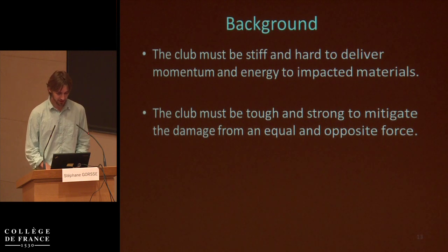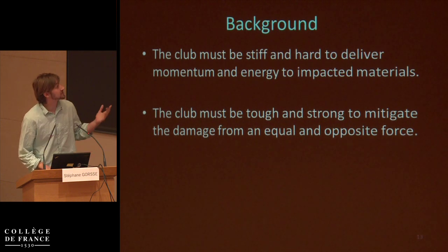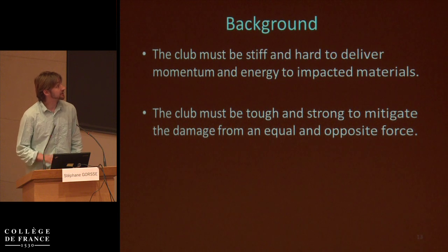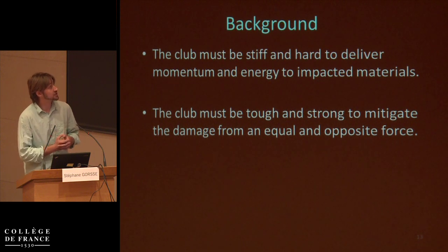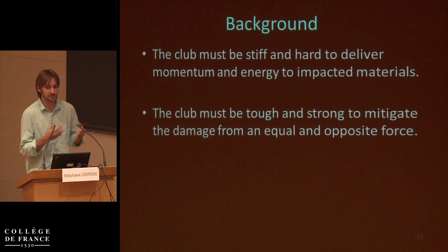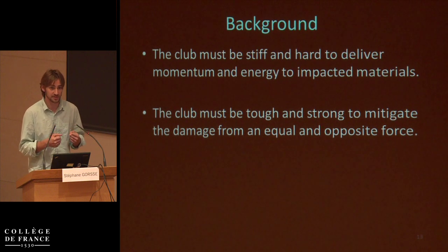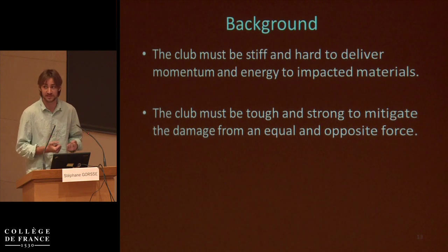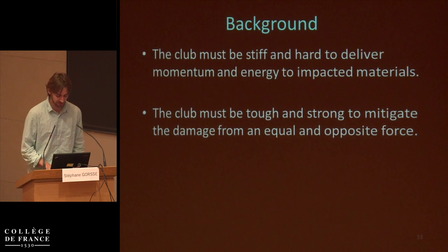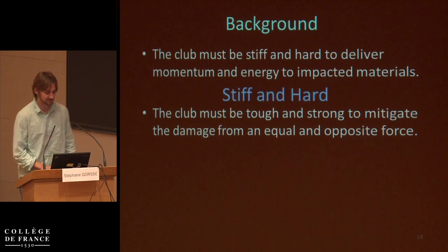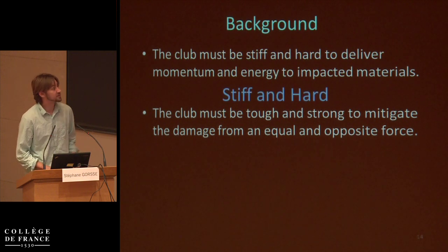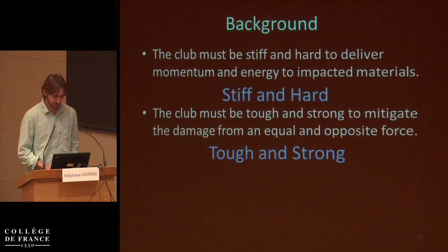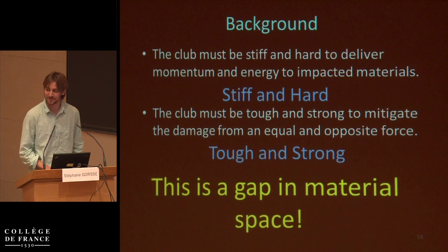So a few things that we can say about the club from this process. One is that in order to deliver energy and momentum to something, it's proportional to the difference in the modulus between those two objects. So it needs to be as stiff as possible because it's combating very stiff prey. So it must be very stiff and very hard. But then it also must be very tough and very strong in order to mitigate the damage from that equal and opposite force. So these four things together, I mean, that's a gap in material space.